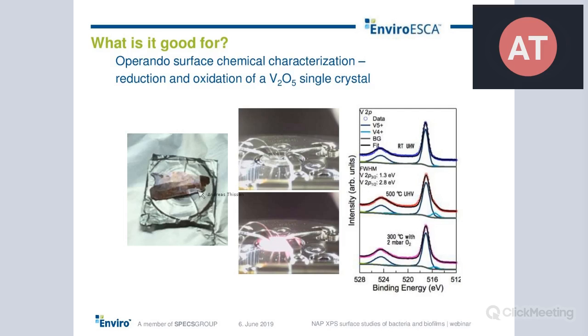And we have used a heater to reduce and reoxidize the vanadium pentoxide. So we started with just inserted and freshly cleaved vanadium pentoxide. This is a vanadium 2p signal here. Vanadium pentoxide means, under this stoichiometry, that vanadium is in the stoichiometric compound in 5+ state. This is shown here. When you now start to heat it up in vacuum up to 500 degrees C, then you lose oxygen, it is reduced. And you see that due to the reduction, vanadium is reduced from 5+ to 4+ state. This is what you can see here.